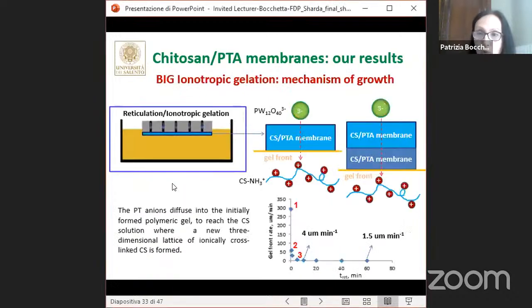So we have tried to monitor the ionotropic gelation with time by measuring the membrane thickness by SEM of the prepared membranes formed at different gelation times and at fixed chitosan concentration. Basically, three main steps are involved, as you can see here in the sketch. In the first step, named 1 in the figure, we are in the first seconds of alumina immersion in the chitosan solution, and so anions of the acid and chitosan amine groups come in contact at the interface and immediately react, as expected for electrostatic ionic bond formation. This is translated into a high initial gelation front rate, after which